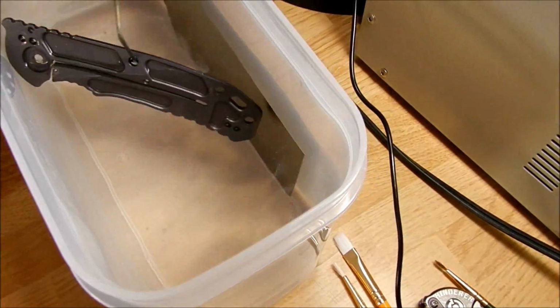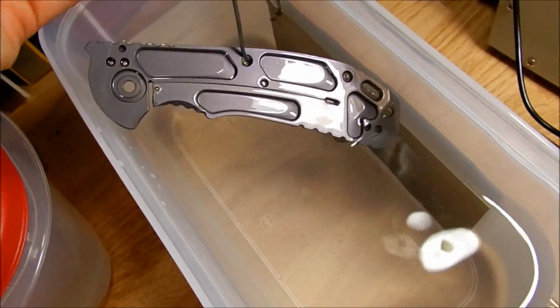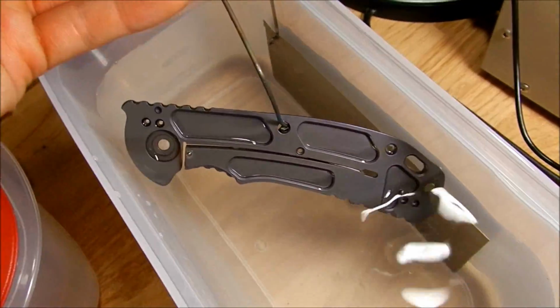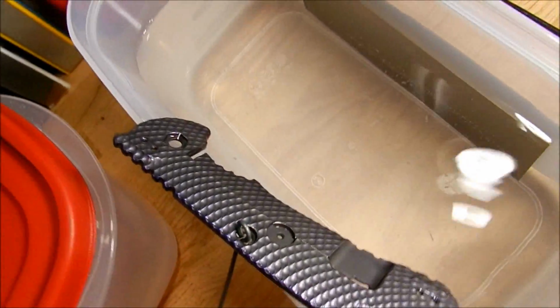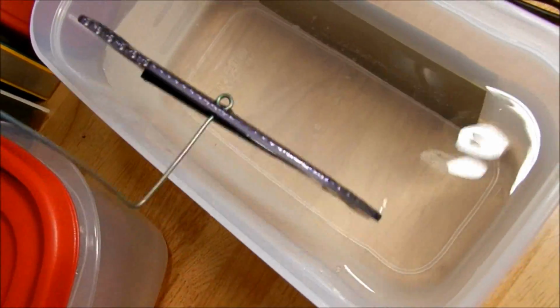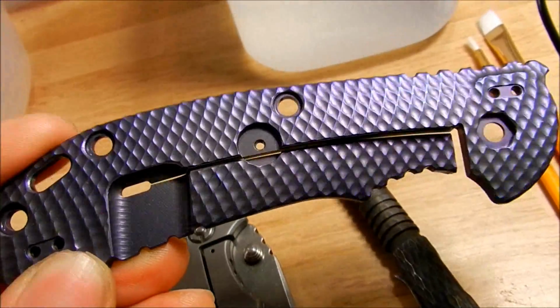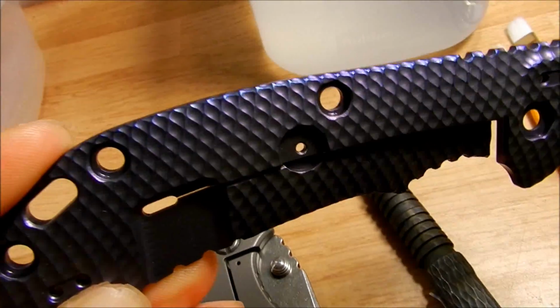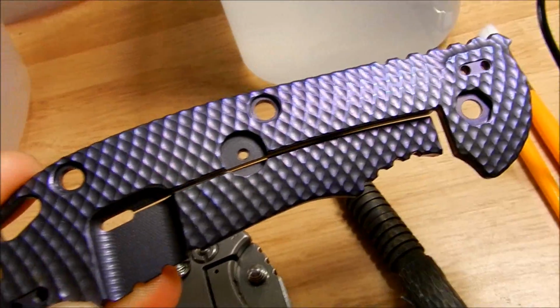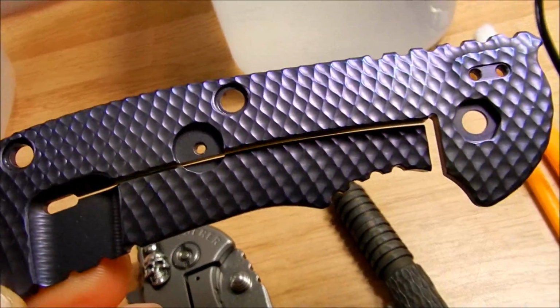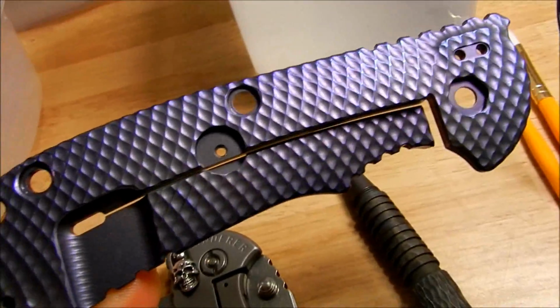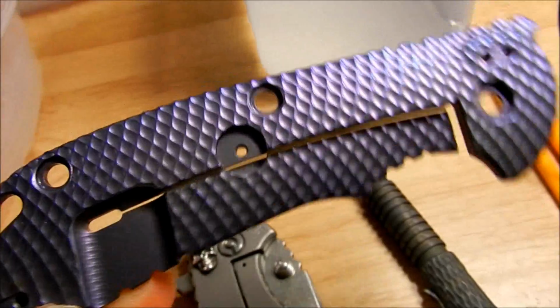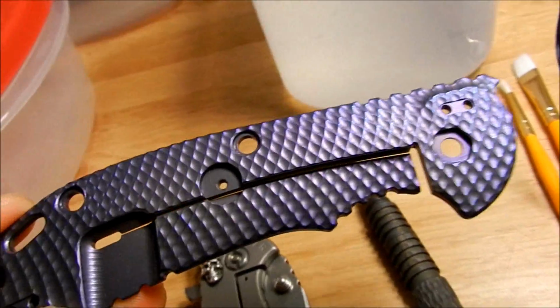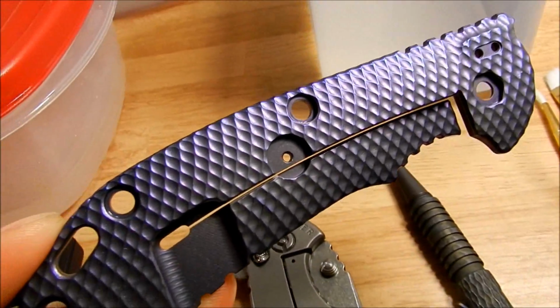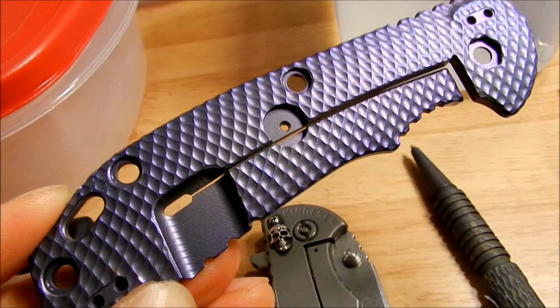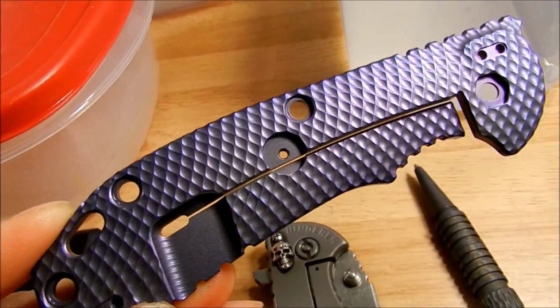Let's see what kind of color we got here. As you can see, not very good looking. Not very blue. This is what it came out looking like. See, on the edges, like on the corners, it seems like it's a very vibrant blue, but in the middle, it's like there's a gray coating on there, and that's that cloudiness I was talking about if you leave it in there too long, or if you don't keep it in distilled water after transporting it out of the multi-etch.